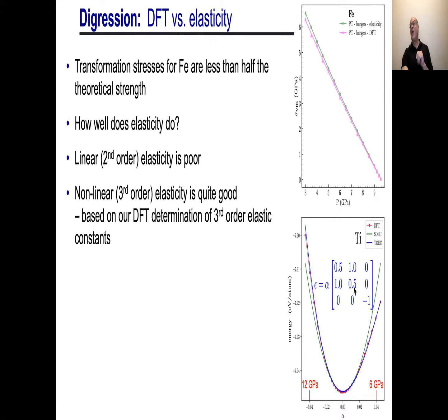So here we applied an arbitrary strain and just increase its magnitude, alpha here, for an arbitrary strain tensor. And what you see here is the energy as a function of strain. The red points are DFT. The green points are from second order elastic constants. The blue curves are third order elastic constants. And so by the time you get to third order, you do a pretty good job of reproducing the DFT. So what we're going to do is use the third order elastic constants in order to simplify the calculations we're going to do with DFT. I'll show you that in a little bit.